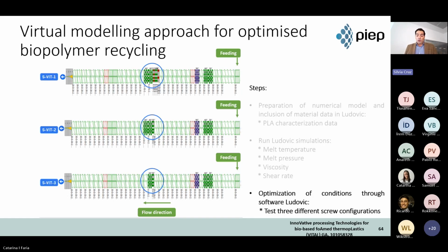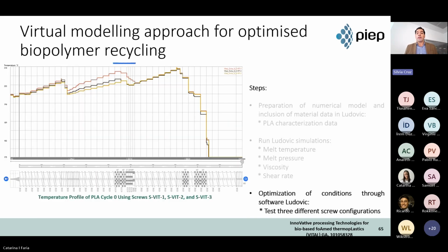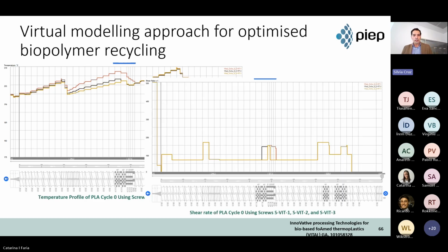With this optimization of the screws, again, we run the simulations, and what we get immediately was a decrease in the temperature profiles of the material, a clear indication that, of course, the shear rates of the material were lower, and we get, at least as expected, less degradation of the material. We also noticed a strange result of the simulation regarding shear rate. Of course, we changed the length of the mixing zone, but there were some unexpected results in these differences in the shear rate that we get from the software.